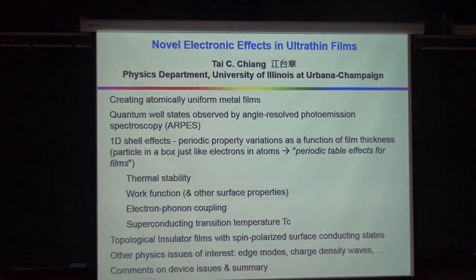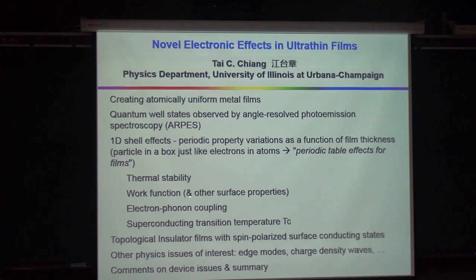And just like in atoms, where electrons are confined in atoms. So in the atom, you have a 3D situation. In thin films, we have a one dimensional situation. But even in this one dimensional case, you have periodic table effects in films. It's just like atoms. You go from one atom to the next, you add electrons. In the films, you make it thicker, and you add even more electrons to your filled shells in the same way. So I'll demonstrate that this leads to periodic oscillations in thermal stability, work function, and electron-phonon coupling, and I'll mention briefly the superconducting transition temperature because that's related to the strength of the coupling between electrons and phonons.